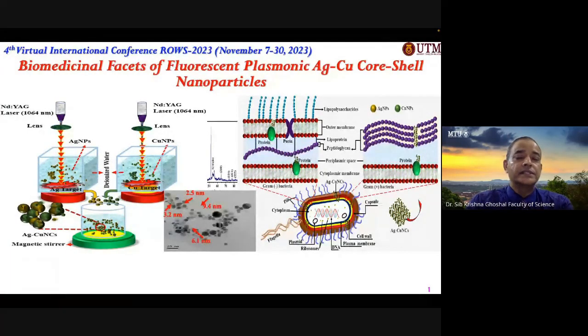And then we mix this silver and copper colloidal suspension to form the core shell nanoparticles. We need to also verify whether they are really core shell, or they are nanohybrid, or they are nanocluster. So this is also another part of the game. And then after these nanoparticles are characterized, their properties are optimized, we choose the best nanoparticle, then apply it on the bacterial strain, and look at the death of the bacteria over time by optical density measurements, by inhibition zone boundary measurement. So one is the biomedical aspect of this nanoparticle, and the other is the physical properties determination of this nanoparticle starting from the production.